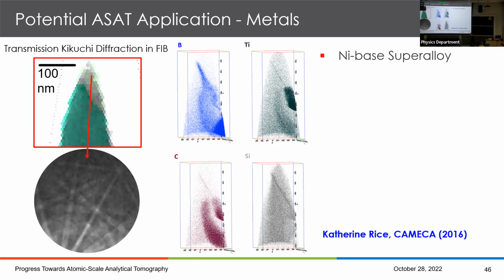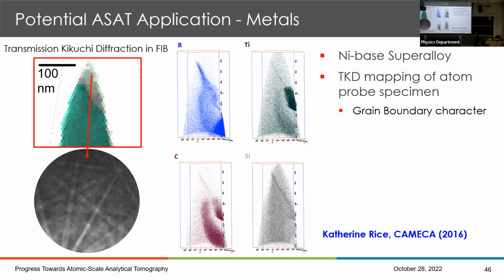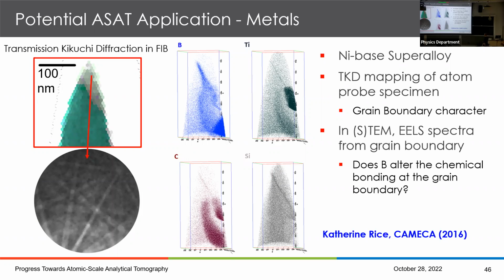But then wait a minute, how do we know that? Is that the cause? Just because I see boron on that grain boundary, does that mean that that's causing grain boundary embrittlement? Well, could you say anything about the bonding at that boundary? Has that affected it? To me, this is what I'm getting at: in this work, Katie didn't have that, but if you have this in the electron microscope, one of the first things you want to do is say, okay, can we get EELS information? Tell us if the boron, or these other elements, are affecting the bonding across that interface. This is making the point that you want to have chemical information supplementing just the raw compositional information if you're really going to be able to draw hard scientific results.